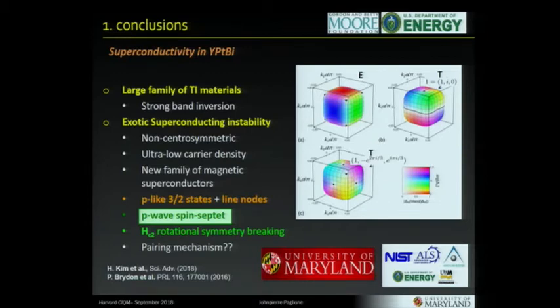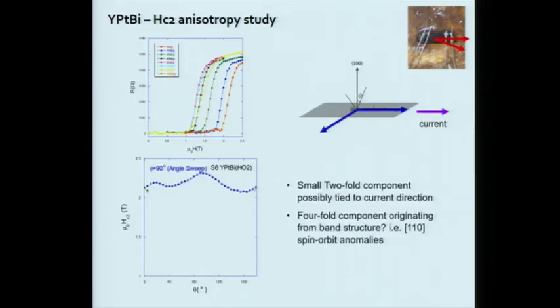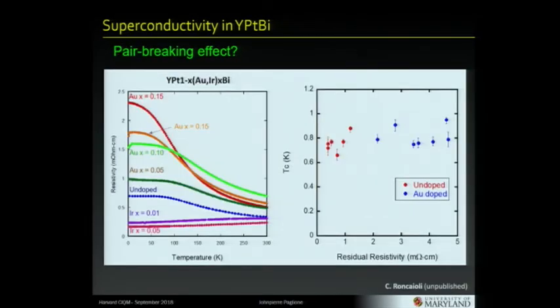The carrier density is quite low. I wonder whether you can dope this crystal with something else and just try to tune this carrier density. That was what we tried, but gold is probably the same valence as platinum and doesn't change it. We were excited when we saw that. Of course, we wanted to tune to the band touching point, and we were excited when we saw this. But when we did some Hall effect and even quantum oscillations, it didn't look like it changed. So we don't know why this is actually going up. It's maybe a disorder effect.